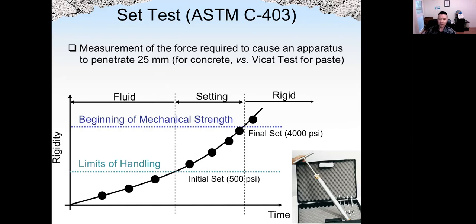For concrete, it's pretty much similar, but we use this penetration apparatus. This machine can measure how much pressure, how many psi, it takes for the spindle to penetrate the concrete samples. So we just use this penetration apparatus around every 5 minutes or 10 minutes. For many different test points, we can connect the points as a curve. The initial setting time corresponds to 500 psi, psi being pounds per square inch. And the final setting time is the time when the penetration resistance corresponds to 4,000 psi, or 4 ksi.